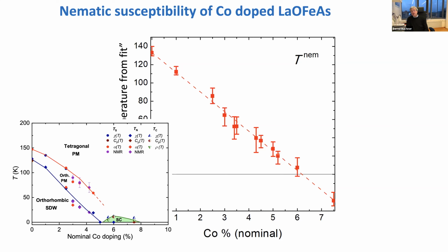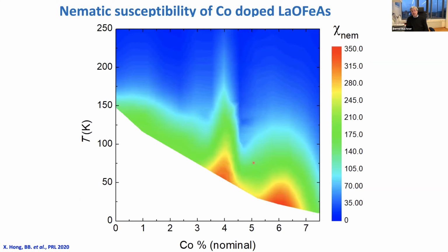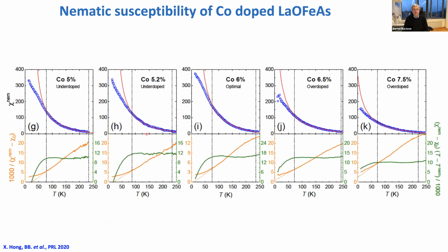Not only can we look at the nematic transition temperature, we can also look at the susceptibility. What I've plotted here is just the absolute value of the strain derivative, and it's raw data, nothing is done with it. At optimal doping we have a pretty large number here, so there's a very strong change of the resistivity as a function of strain. If you go to overdoping, it becomes much smaller.